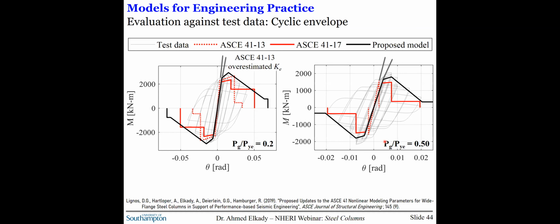Also, for the previous standard, as I just mentioned, for a column subjected to 50% of its axial yield strength, you would consider this cyclic envelope curve, where essentially you have the elastic region, and then you drop right away in strength because you don't have plastic deformation, which is a force-controlled limit. Again, this has been revised as I just showed.